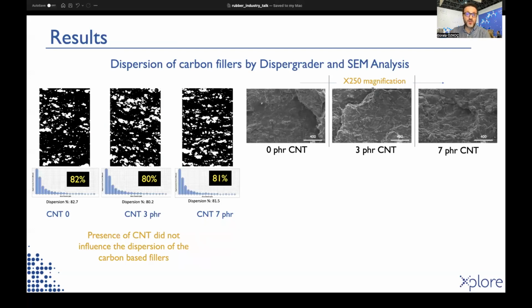We analyzed the dispersion of the fillers using dispergrader and electron microscopy. When we focus on the dispersion, we don't observe any agglomeration of the fillers or obvious phase separation of the matrix, which is NR and SBR. The homogeneity of the samples was good.